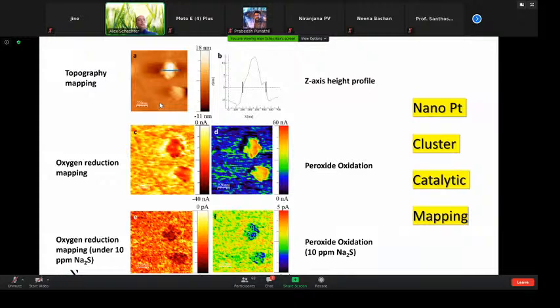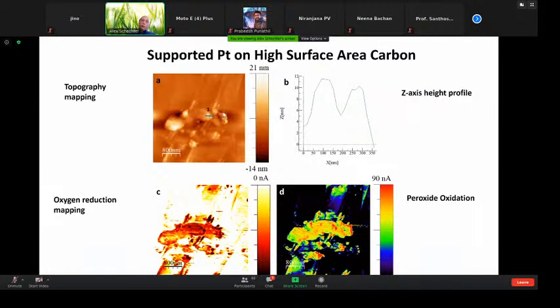Here we're measuring the cluster and the supported catalyst. We can say exactly where the catalyst is located over a carbon support. Different locations, different spots, and this is just by looking at the oxygen mapping. If you look at the image, for example, this is the AFM image. You cannot detect where the platinum is. You see here 2 particles. You see here this can be carbon or something else. But when you look at the dark spots here, these are for sure platinum catalysts, and we can identify exactly where the catalyst is. So most of the current is coming from these spots, but the utilization is low.